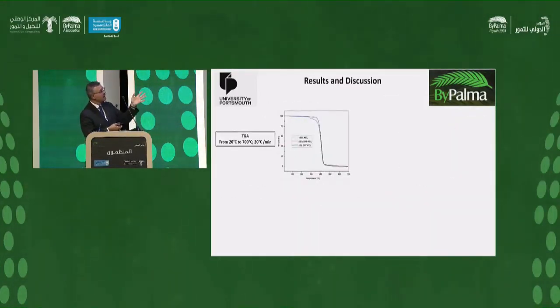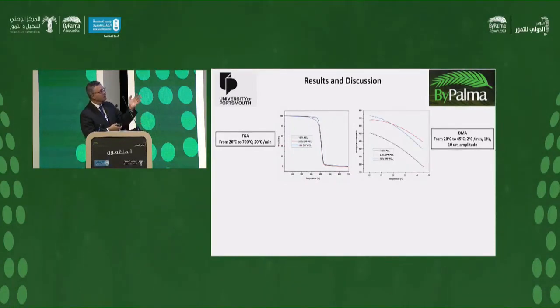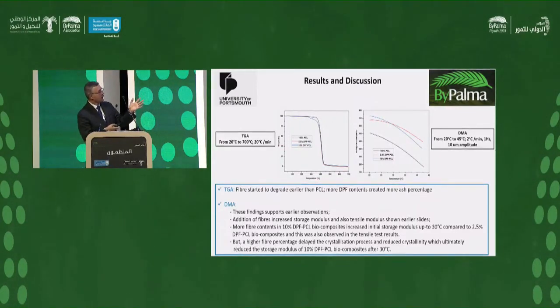So on TGA, we have some results. Fiber started to degrade earlier than PCL. More date palm fiber content created a higher ash percentage. So this is another finding that we have got here. From DMA results, the storage modulus and loss modulus have increased with the date palm fiber inclusion.